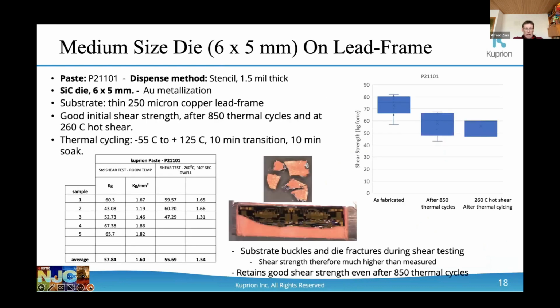So some bonding characteristics. We have done a lot of bonding, as you can see, from 1x1, 2x2, 3x3, 5x5, and lots of other sizes, up to 15x15 on our CTE adjusted substrate. This is a 6x5 on a thin lead frame that gave very good results. Even after 850 thermal cycles, it still looks very good. Hot shear is almost the same after thermal cycling. So we get very good bond data for a wide variety of die.